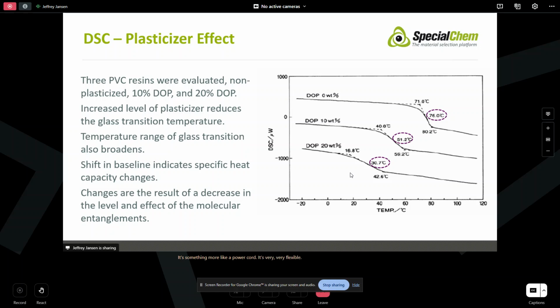What happens is that the increased level of plasticizer changes those physical properties, but that's really tied to the fact that it also reduces the glass transition temperature of the material. We can see that our unplasticized PVC glass transitions around 76. As we add increasing levels of dioctyl phthalate, we drastically reduce the glass transition temperature of the material.